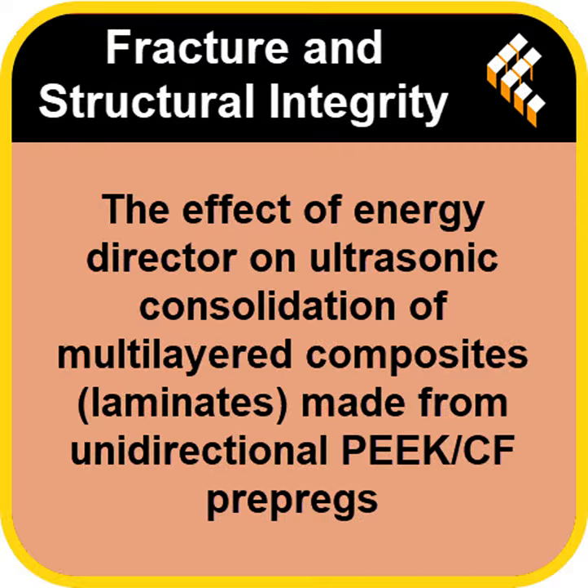Why wasn't that just declared the best outcome? If strength is the goal, why settle for less? Because in engineering, reliability and structural integrity outweigh pure strength if that strength comes at a hidden cost. The researchers specifically rejected that 60 MPa value because achieving it at 1200 milliseconds required so much energy, so much melting, that it was causing microscopic damage to the original carbon fiber structures.